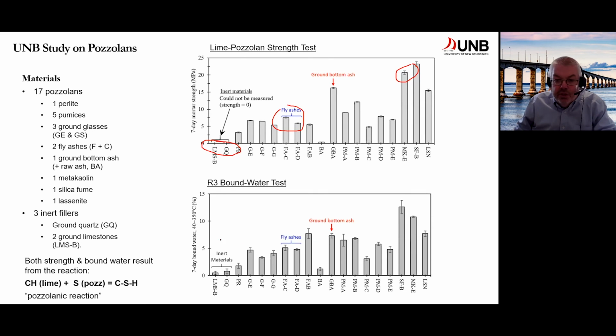And generally, there's a good correlation with the bound water test from ASTM. Or this is the Rilem test that ASTM has now adopted. And this is a fairly simple test to do and only really requires access to an oven that can heat up to 350 degrees Celsius.